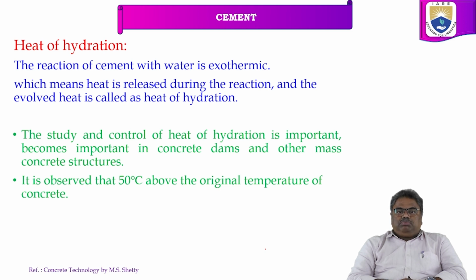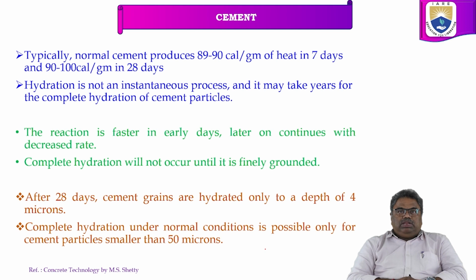During that process, heat of hydration will be very high. It is observed that the temperature can rise 50 degrees centigrade above the original temperature of the concrete.